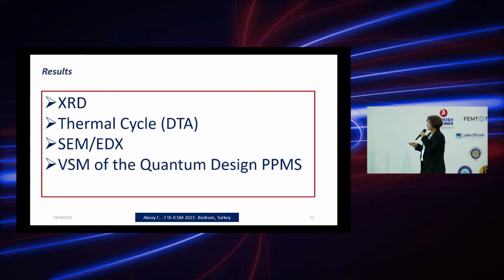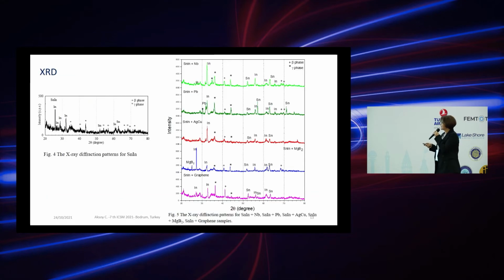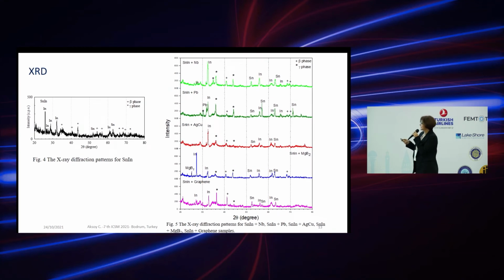So we did microstructural and superconducting characterization, and the results are shown here. The first graph is the X-ray diffraction patterns of tin-indium, and the others are with the addition materials. Here you can see the beta phase and the gamma phase, marked with stars and plus signs, and the niobium, lead, silver, copper, magnesium diboride, and graphene additions. The intensity of the gamma phase and beta phase reduces when the additions dissolve in the tin-indium solution.